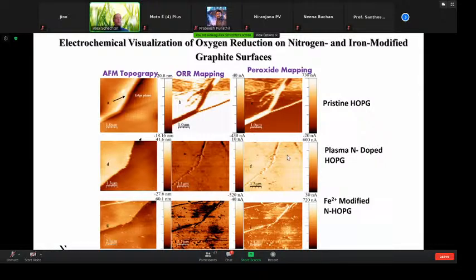Now, a second or third step will be to dope it with some other atom or element. And in this case, we use iron. And you can see the iron effect adhering to the same active site or hotspot that was previously doped by the nitrogen and gives us higher current. That was published 2 years ago right now.